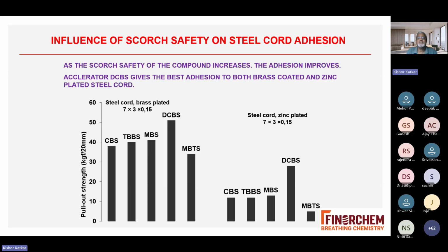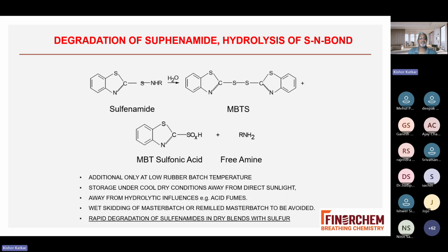A lot of non-tire industry also use steel cords or steel wire. So you require a good bonding between rubber and steel, because it's a composite of rubber compound and steel. You require sufficient scorch safety so that the bonding takes place before the vulcanization starts. Otherwise, once the compound is cured, no bonding will happen and there will be failure. So DCBS gives the highest scorch safety and the highest bond strength when you are talking about the pull-out strength of the steel cord.